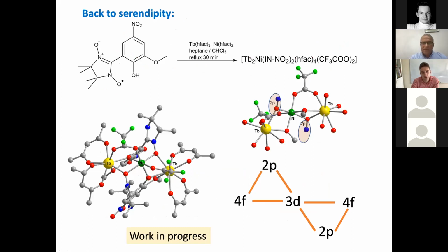So back to serendipity. We employed the ligand I discussed before in a one-pot reaction with a 3d and a 4f metal ion. And we obtained a 3-nuclear compound, and again with this triangular topology. So for the moment, I present here only the structure of this new example of a system containing 2 aminoxyl groups acting as bridges between two different metal ions. So actually, we doubled our first triangle we reported before.